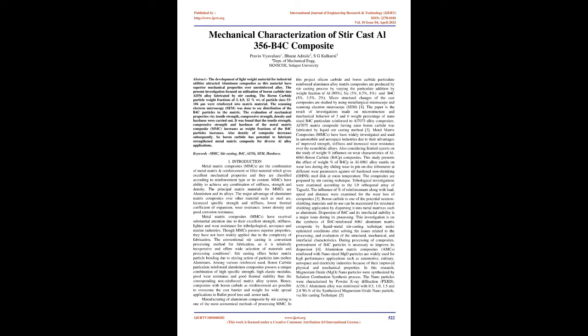In this project, silicon carbide and boron carbide particulate reinforced aluminum alloy matrix composites are produced by the stir casting process by varying the particulate addition by weight fraction of Al 90%, SiC 5%, 6.5%, 8%, and B4C 5%, 3.5%, 2%. Microstructural changes of the cast composites are studied using a metallurgical microscope and scanning electron microscope, SEM. 2. The paper is the result of investigations made on the microstructure and mechanical behavior of 3 and 6 weight percentage of nano-sized B4C particulate reinforced Al7075 alloy composites.